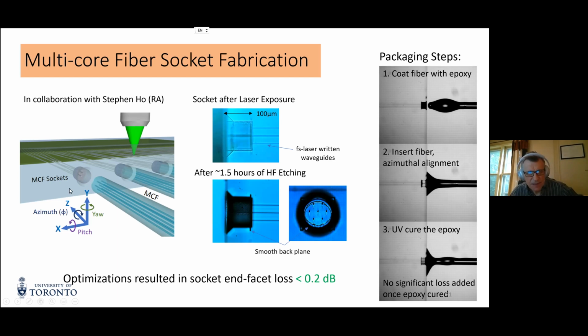Firstly, what we do is we scan the laser and chemically etch these sockets. And what this does is the fiber can just plug in and just rotate to the best alignment. This saves a lot: from 6 dimensions of alignment, it just becomes 1 dimension of final rotation to lock in and light up the circuits.